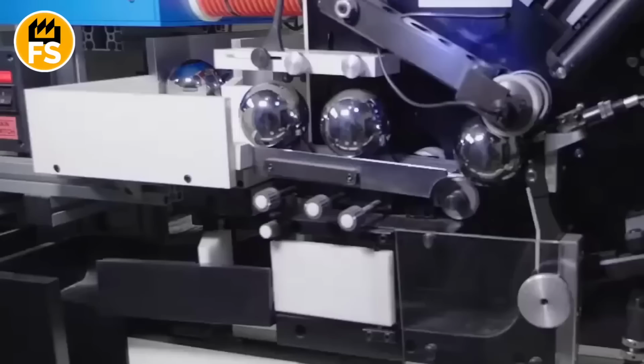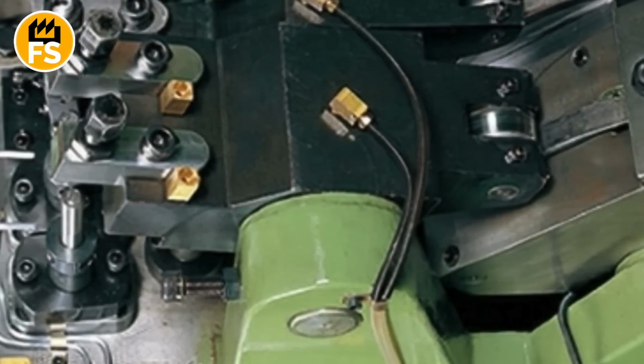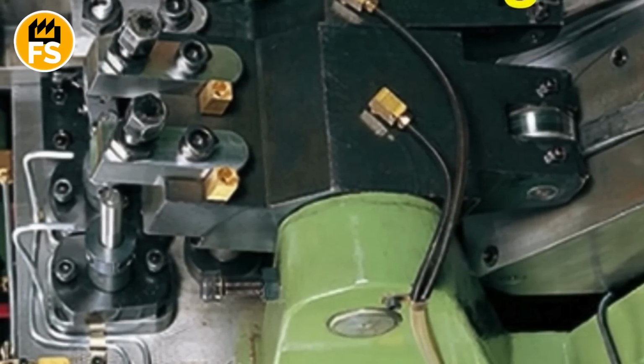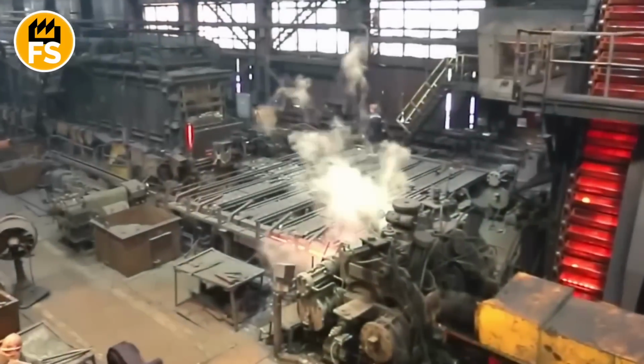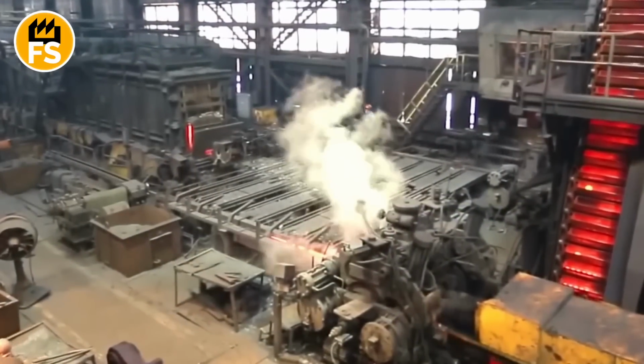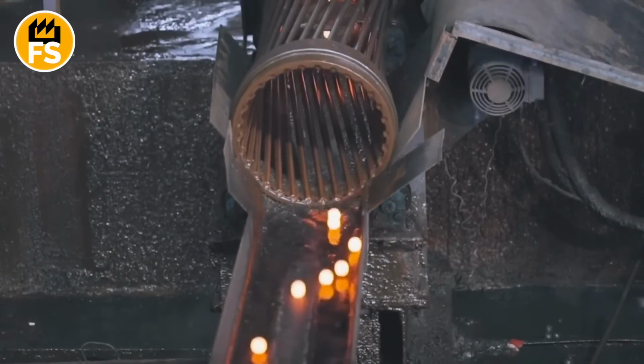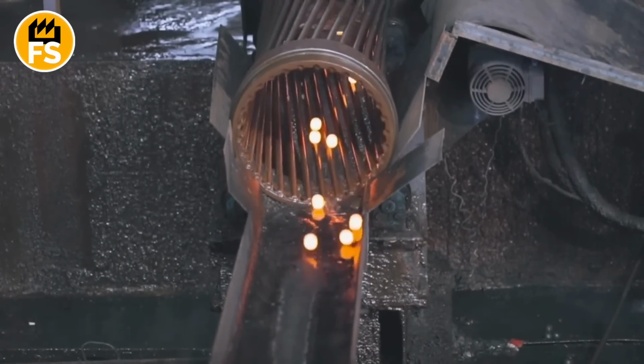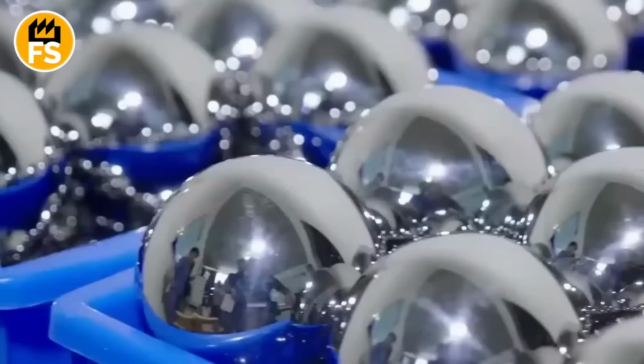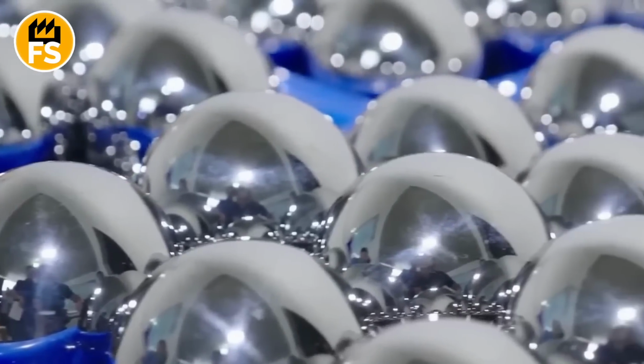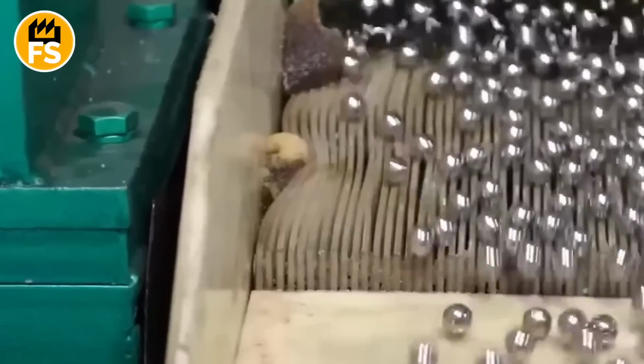Next is the tumbling process, where the blanks are passed between two discs spinning at incredible speeds, up to 1,800 revolutions per minute. This removes the seams and achieves a more perfect shape. Then comes heat treatment at 1,500 degrees Fahrenheit to give the steel strength, and only after that, the finest grinding. The balls are ground on high-precision machines with a tolerance no greater than 4 millionths of an inch. Polishing takes 48 hours, and the final result is a ball that can rotate millions of times without wear.